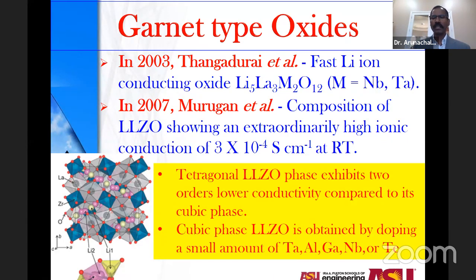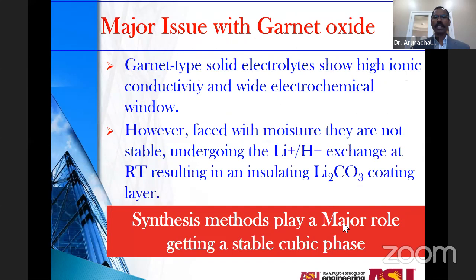But again, there are reports that this material can become less stable if it is exposed for a longer duration to moisture, where lithium can be exchanged with protons. Many researchers still question the stability of these materials: we think it's a lithium conducting garnet structure, but because of the instability in moisture, can it become a proton conductor? If that happens, the battery is not going to work with lithium. So it is a very important feature that the structure has to be very stable, with an appropriate synthesis method to obtain this relatively metastable cubic lithium lanthanum zirconium structure.